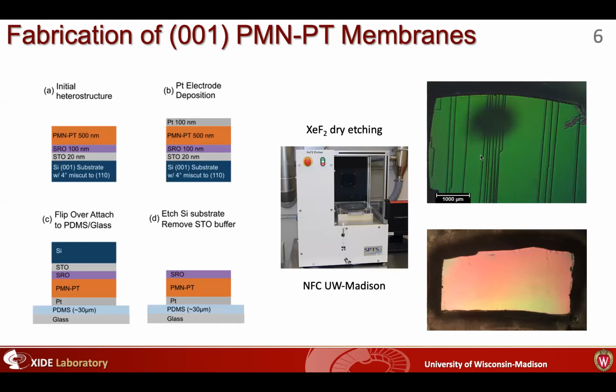So I'll spare some of the gory details of the fabrication of these membranes, but I'll highlight how we make them freestanding. We would grow these on STO buffered silicon 001 substrates. And then I deposit a platinum electrode on the top so that I can flip it over and attach it to this PDMS and glass soft polymer platform. So I still need stability for handling, but using a xenon difluoride dry etching method, we could completely remove the silicon substrate. And in some samples, you do see a lot of cracking.